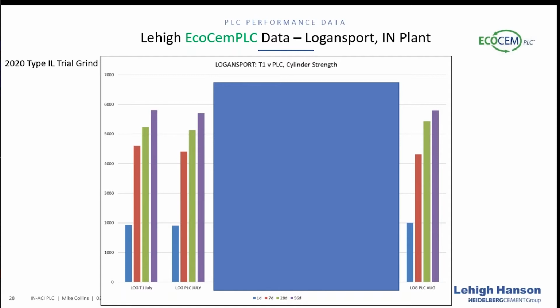That's kind of the like for like that we're looking at. So let's verify it. We did a second trial grind in August, and that's on the very far right. When you look at that strength data, again, right in line with where our Type 1 is, and I would even say a little better in some categories, especially 28 and 56 days. And if you look at the 1-day break on the PLC in August, it's the highest of the three. So again, like for like performance or better.